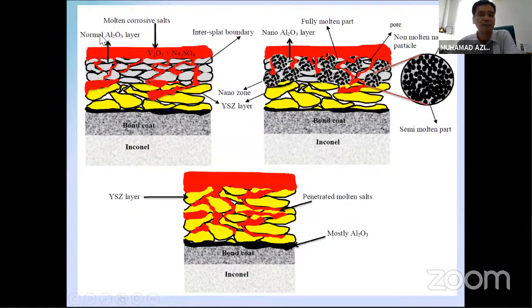If you have the normal alumina, you can reduce it a bit, because you have another barrier layer here, the gray color. But if this layer is made from nano size, we can further prevent it. Why? Because when you deposit coatings of nanostructure, the nanostructure will be preserved. Based on our observation, we can see the nanostructure remains in the coating. So this nanostructure will prevent the corrosive salts from going through the ceramic towards the bond coat, which reduces the formation of thick TGO layer.